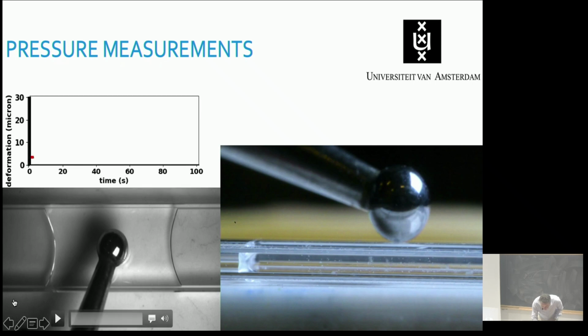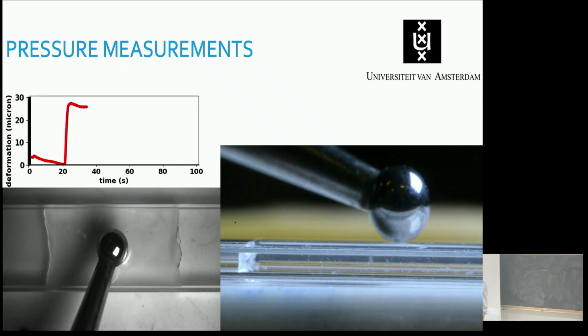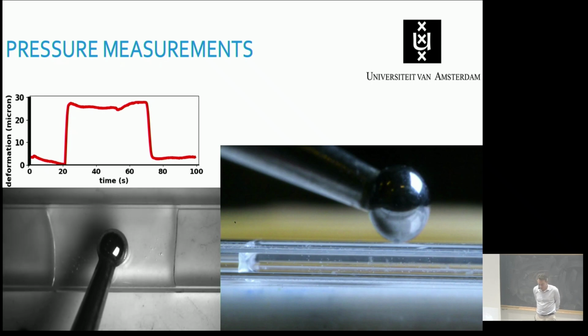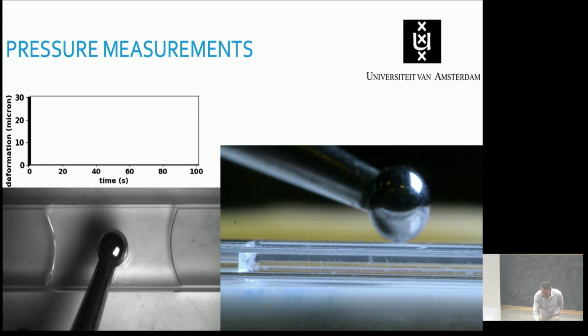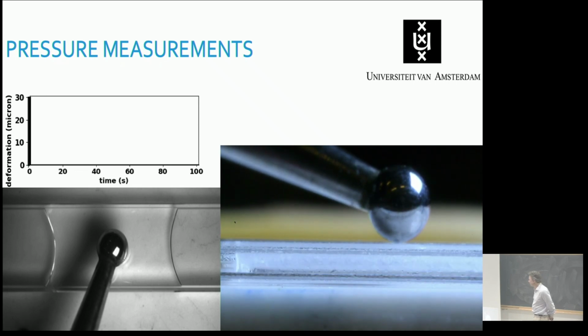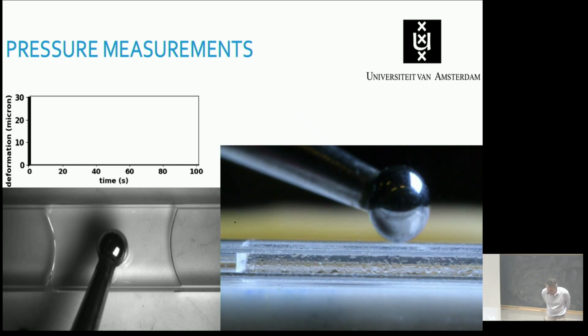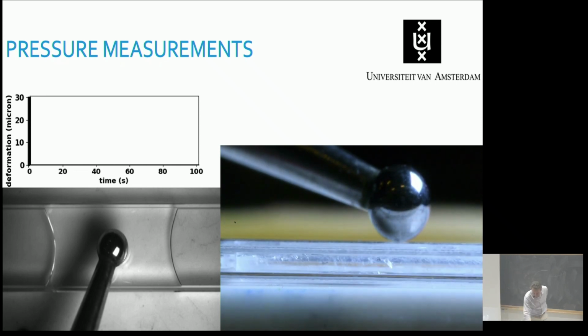And so what happens is we cool, and at some point it freezes. Then we get a displacement of our cantilever. And then we heat it up again. The cantilever goes back to its initial position, and the ice retransforms into water. If you don't believe that the cantilever moves, you can have a very careful look at this movie. But you really have to look very carefully. You see it? So this is everything we need to know, except for the fact that we only have a displacement, and what we really want to have is a pressure.